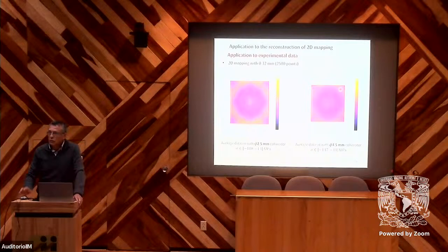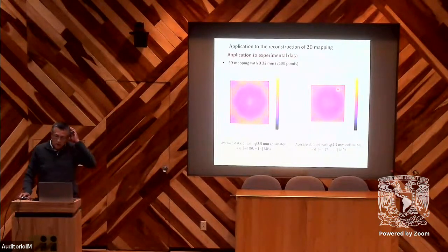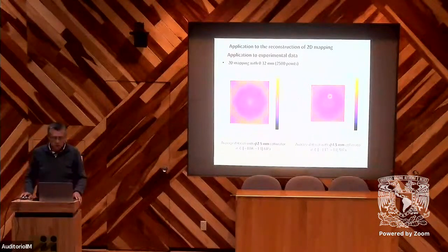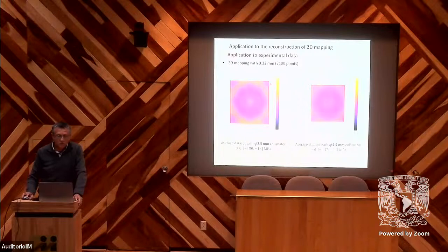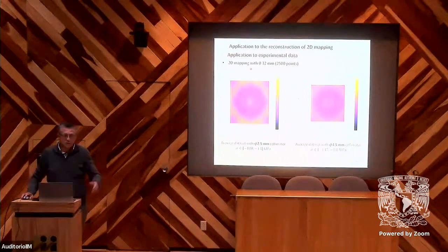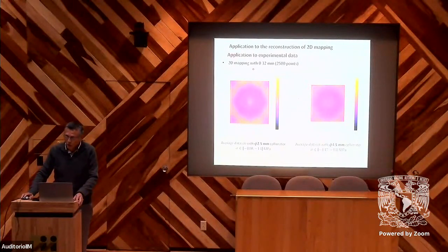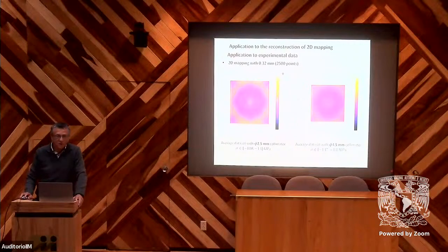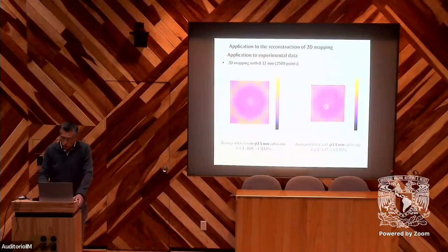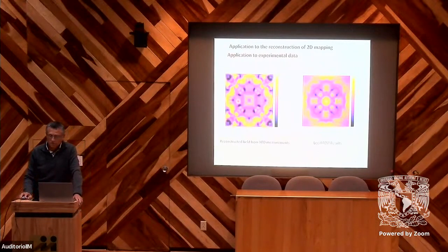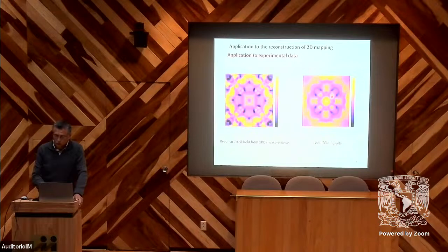We also extend this approach to mapping in two dimensions, and we observe here the problem is the number of points. The method can be very long because if we use here 50 by 50 points, we have 2,500 points. Each point can take perhaps half an hour or more. It means a very long time to get this. This is an inconvenience of our method, but this is the map obtained with the small spot, and this is for the higher spot. From these two maps, we can obtain this one, and then we can compare to our reference obtained by finite element method.